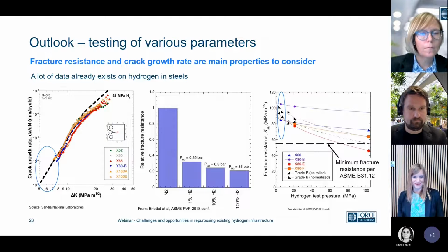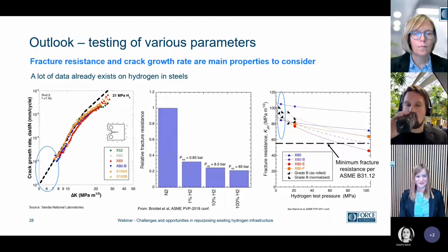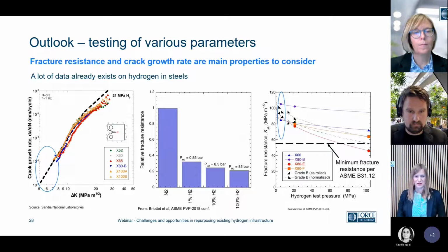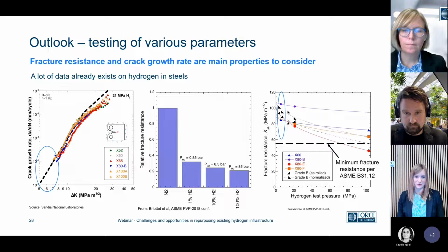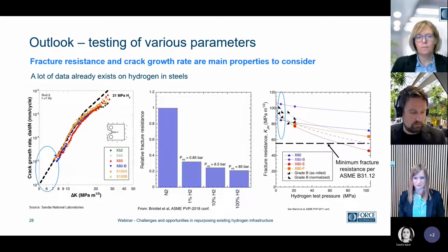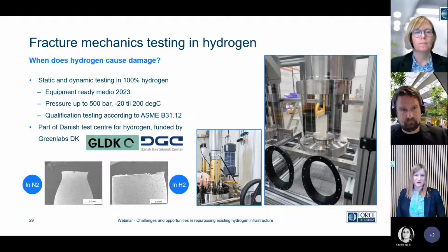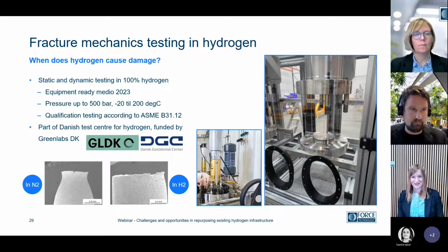The center image is an example of relative fracture resistance in air or nitrogen compared to 1% hydrogen up to 100%. We don't see a significant difference between 1% versus 100%. And that's very relevant for the blending discussion. Similarly, here we see the ASME fracture resistance limits and X60 to X80 steels performing well at various hydrogen test pressures. So fracture mechanics testing is still very important because we haven't gotten all the answers yet.